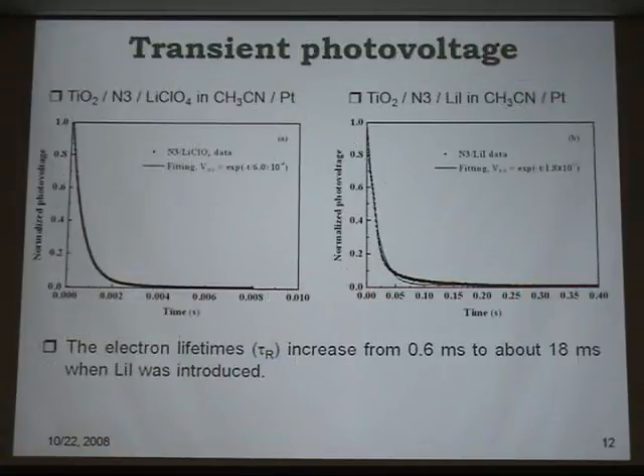Now, just to give you one example how important it is to have the right anion. In dye-sensitized solar cell, we talk about lithium iodide instead of lithium perchlorate, which was used in lithium-ion battery. Now, everything remains the same. The platinum counter-electrode, titanium photoanode, and N3 dye. The only difference is this anion. And with the anion, you look at the so-called photovoltaic transients.